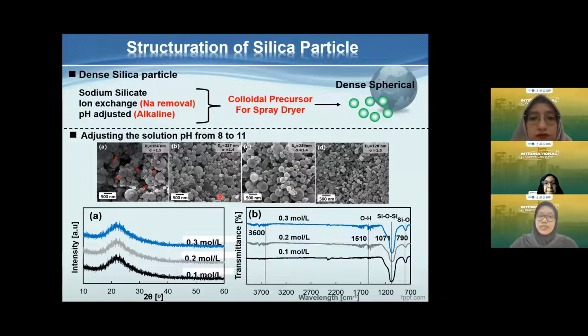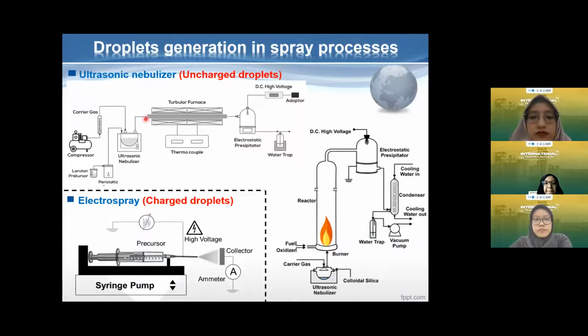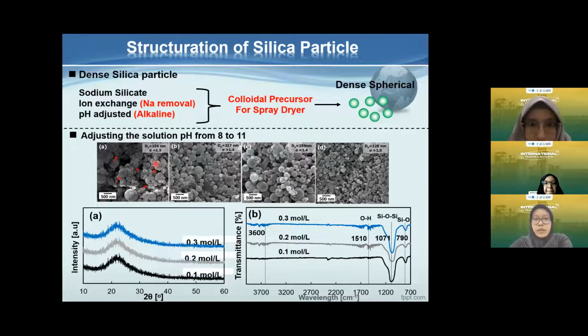This is the result of the silica particles produced using spray drying. There are some kinds of morphologies of silica particles that I have produced. The first is the dense silica particles. Here I use spray drying with the tubular furnace, this one, so I can produce the dense silica particles here. Sorry, I forgot to mention adjusting the solution pH. For the colloidal precursor, I adjusted the solution pH from 8 to 11. As we can see here, all of the particles produced are dense silica particles with different particle sizes.